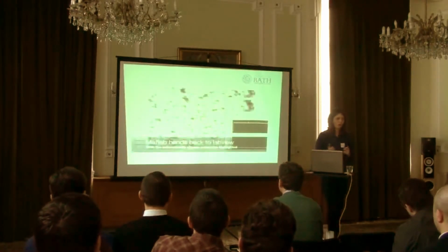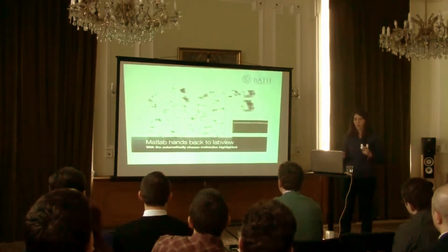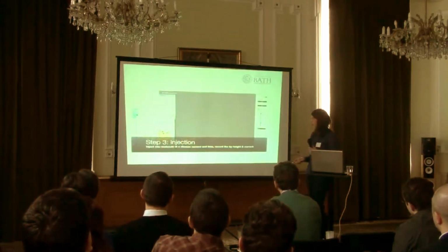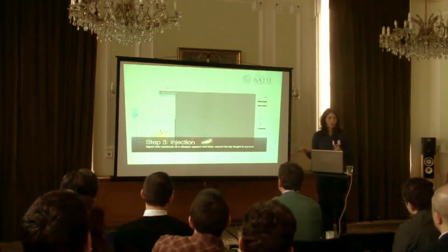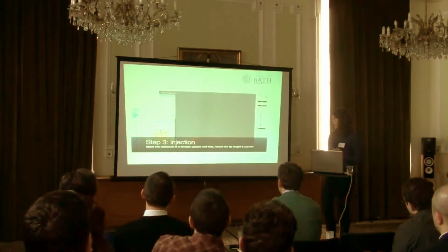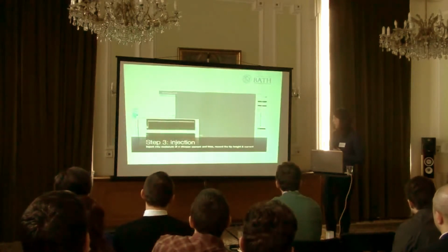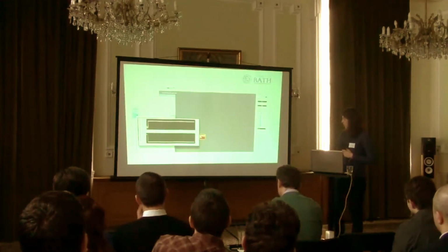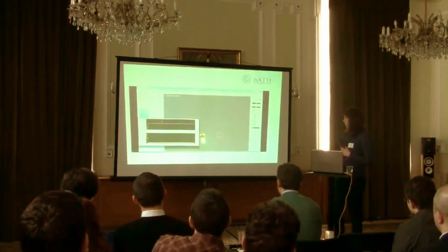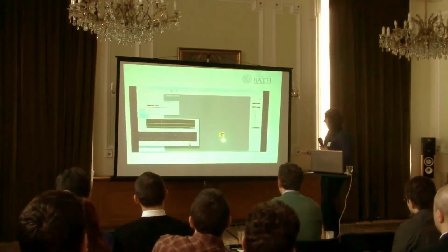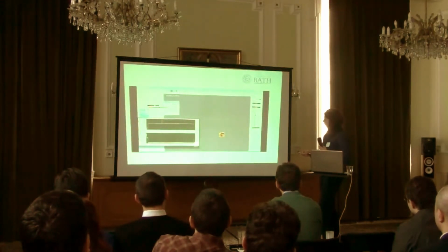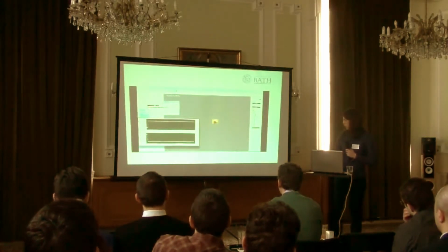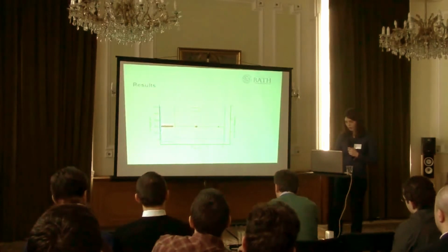The reason why we want to do this is because we're in the regime of quantum mechanics, so everything is probabilistic. To get really nice statistics, you need to do this hundreds of times. And in any other lab, doing one of these experiments is probably going to take the whole of somebody's PhD. So essentially we find all the molecules, we position the STM tip on top of them, we inject electrons and record the height and the current trace and check whether the molecule has left the surface or stayed. I'm going to skip the rest of this video.